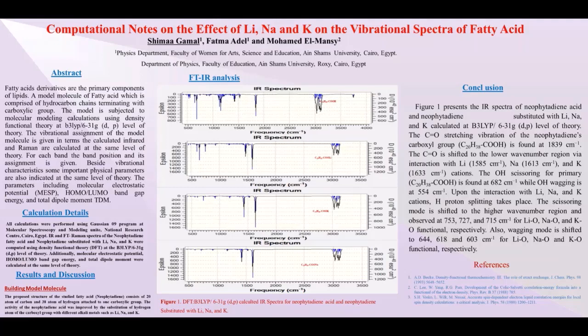The scissoring mode is shifted to the higher wave number region and observed at 753, 727, and 715 centimeters minus 1 for lithium oxygen, sodium oxygen, and potassium oxygen functional respectively. Also, the wagging mode is shifted to 644, 618, and 603 centimeters minus 1 for lithium oxygen, sodium oxygen, and potassium oxygen functional respectively.